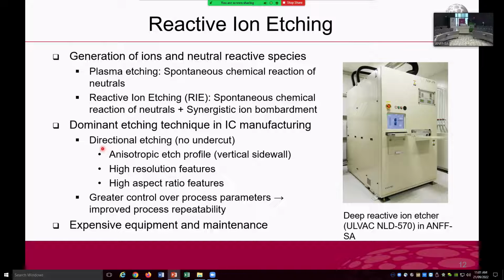And because of this directional etching capability, there is a minimum dimensional shift between the etch mask and the etched features. You can achieve these high resolution features. Also, you can achieve high aspect ratio features. Right? You can make very narrow and very deep cavities by using this directional etching technique.